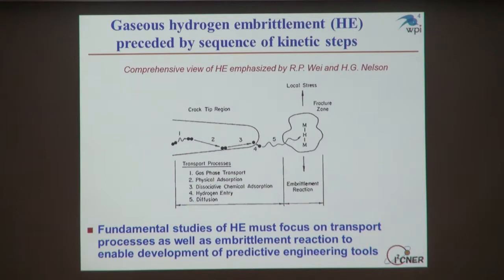One of the realities with hydrogen is that it is not only an effective embrittling agent. There are other effective embrittling agents in materials, elements like sulfur and phosphorus. But what's unique about hydrogen is that it's very mobile at room temperature. What that means is that we don't actually need hydrogen in the material before we load it to get this hydrogen embrittlement phenomenon. We can actually get hydrogen migrating into the material while we're loading it at room temperature. And that's why hydrogen can be such an insidious embrittling agent.